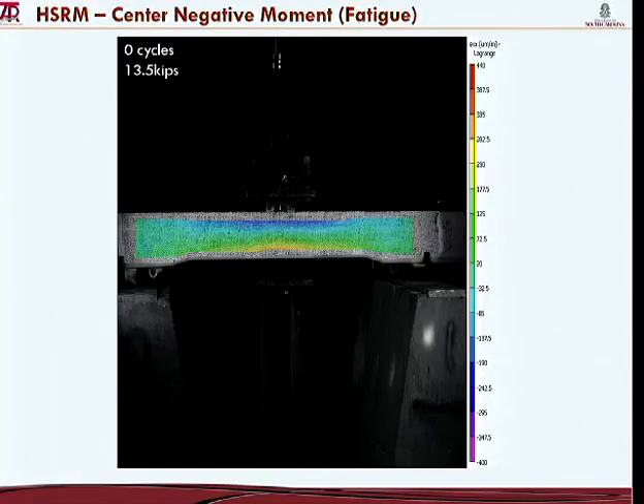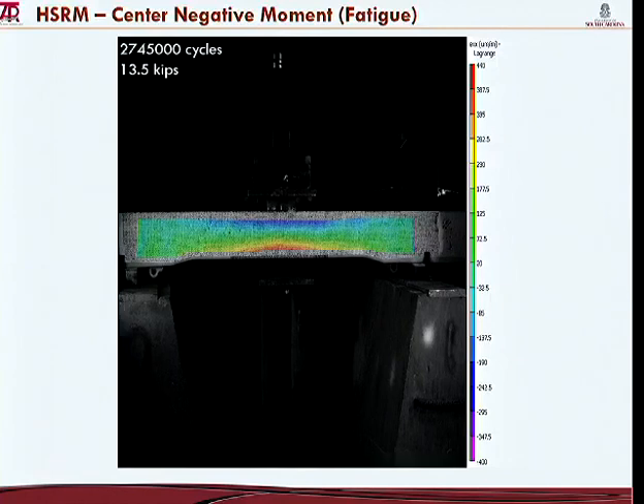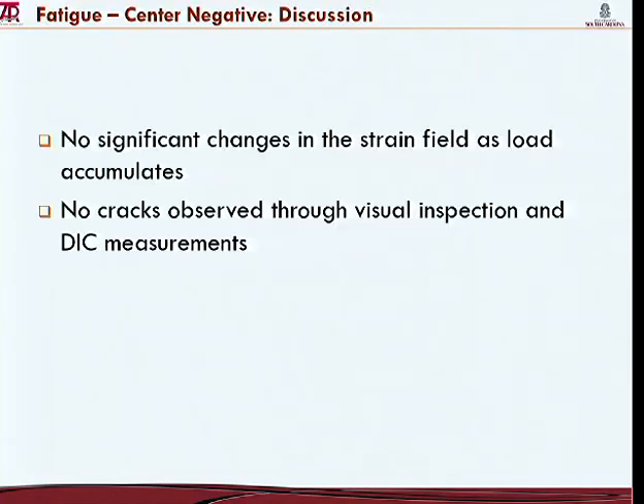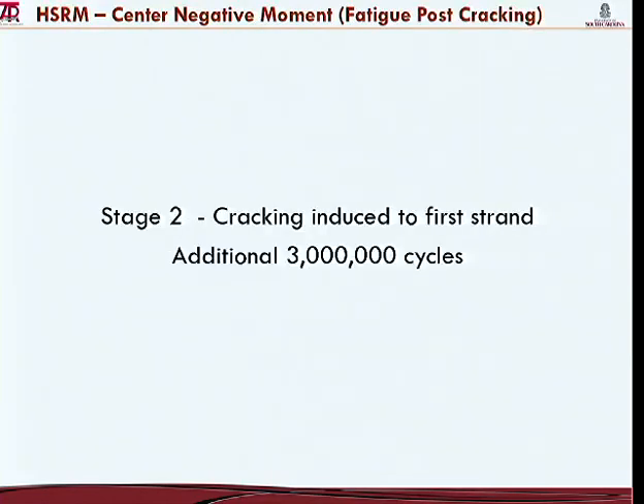This is the 0 cycle. This is at 13.5 kips load. 500,000 cycles, 838,000, over a million. So you see that the strain pattern does not change. No effects here of fatigue load. So no significant change in the strain field as load accumulates. No cracks observed. Stage 2, crack the specimen, another 3 million cycles.